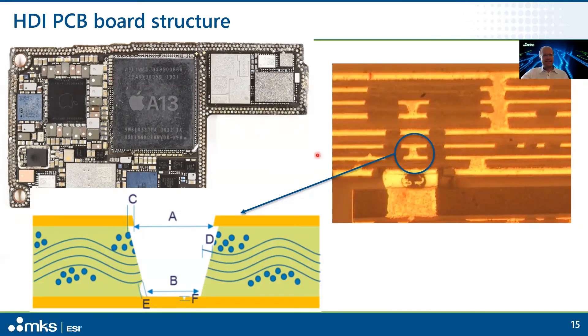The challenge is actually harder than you might expect. You're trying to get through copper — often 10 to 12 microns — then through a resin that evaporates very easily, and a glass fiber that doesn't evaporate so easily. On top of that, glass is highly transparent all the way from the near UV through the near IR.